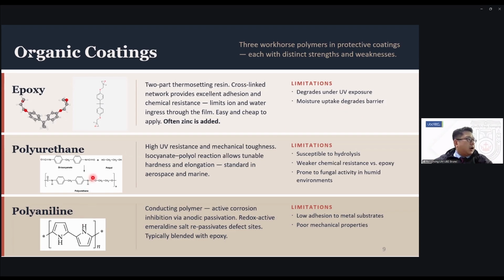The other two, I haven't started looking into them, but you do see them published in literature: polyurethane and polyaniline. What we know about polyurethane is it's got better UV performance than epoxy, so you do see them deployed in commercial coatings outdoors, but it's actually prone to fungal activity in humid environments. And polyaniline, we don't study so much, but it can be blended with epoxy, though it's been shown to have poor mechanical properties, and also doesn't stick to mild steel very well.